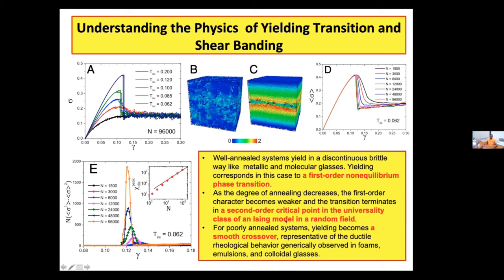So the point they tried to highlight, which is obtained by this Swap Monte Carlo method, is that these various forms of yielding process, brittle, quasi-brittle to ductile, have probably nothing to do with the material itself. It's probably related to their annealing history. So the well annealed glass will always be brittle-like, quasi-brittle will be moderately annealed, and poorly annealed glass is going to always show ductile behavior. And these are questions of interest to many, and further future research is definitely needed to understand whether indeed this is a first order non-equilibrium phase transition.